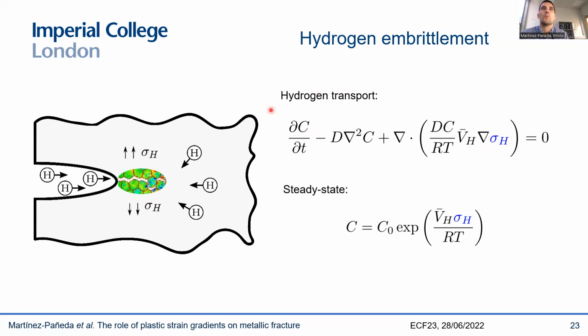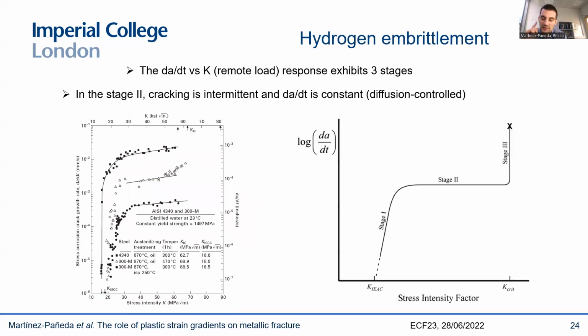This is the simplest equation one can use to simulate hydrogen transport within a metal. And this is the steady state equation, which, as you can see here, shows that there's a very significant dependence on the hydrostatic stress. You know, there's an exponential term here. So if you really want to know what your concentration of hydrogen is, and you really want to know that precisely to be able to predict these hydrogen-assisted failures, you need to know what your hydrostatic stress is. So as you can imagine, GNDs are going to play a big role there. And there's another reason for this.